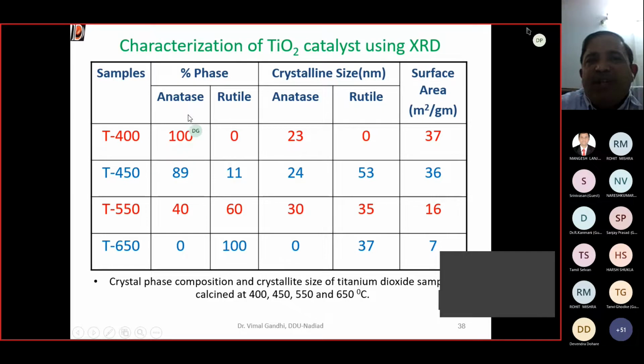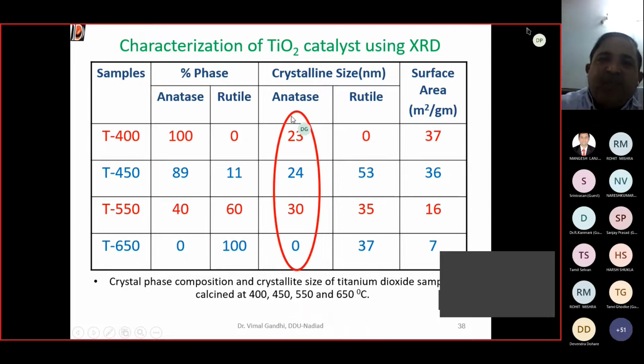It is reported in literature that anatase phase is the most active phase of TiO2, with a crystallite size of 23 nm and an available surface area of 37 square meters per gram. As the calcination temperature increases, the crystallite size also increases because of agglomeration of the particles, which stick with each other, and that's why the available surface area also decreases. At the same time, the increase in calcination temperature leads to increased formation of rutile phase. That means the photocatalytic material is not that active. So you have to be careful when you decide your calcination temperature.